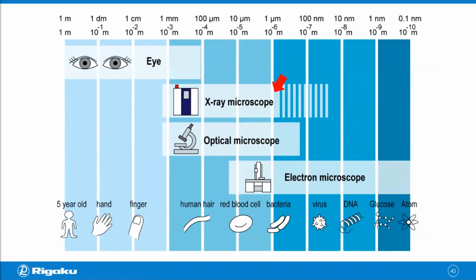Then that is the limit of the X-ray CT technique we're talking about. Technically, you can probably go down to 20 nanometers or so using X-rays, but that often requires synchrotron beamlines. With the commercially available X-ray CT systems, you can go down to 1 micron, sometimes even submicron resolution. Then if you want to see something even smaller, like individual atoms, you're going to need electron microscopes. So that's an overview of the resolution.